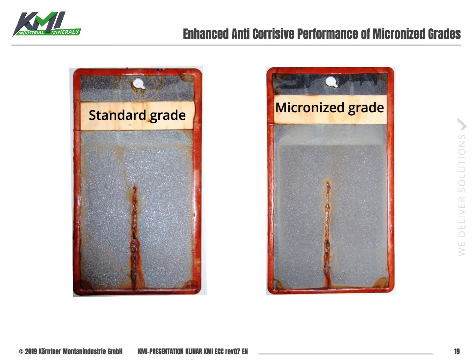The next test is a comparison of this high lamellar standard grade versus the high lamellar micronized grade on the right hand side, and what you can see here, it's another improvement of the performance, especially around the scribe. That means delamination and rusting around the scribe is less than with the standard grades. So that means the micronized grades outperform the standard grades.